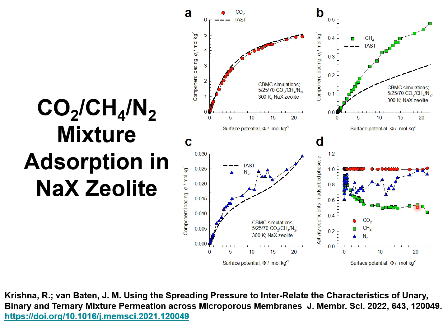The activity coefficients of each of the guest molecules tends to approach unity as the surface potential is approaching a value that is vanishingly small, implying a pore occupancy that is negligible in magnitude.